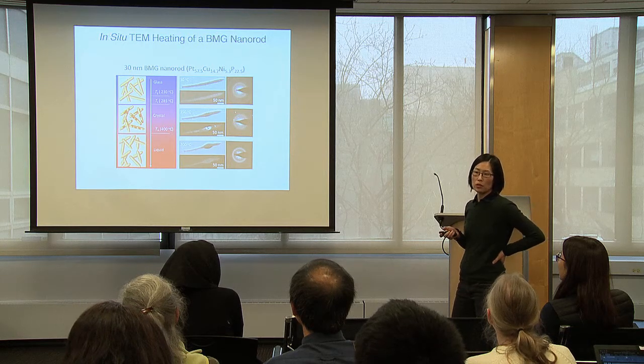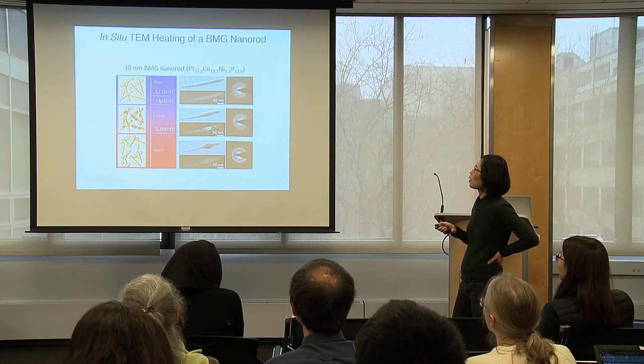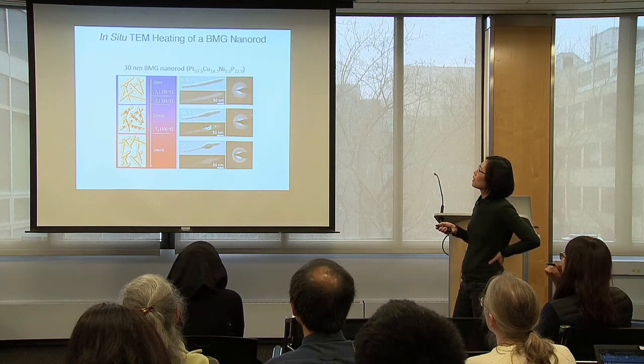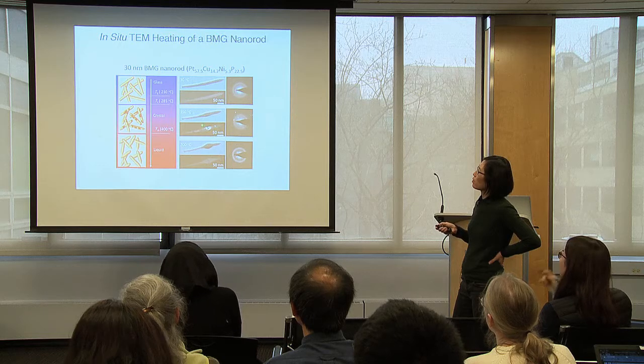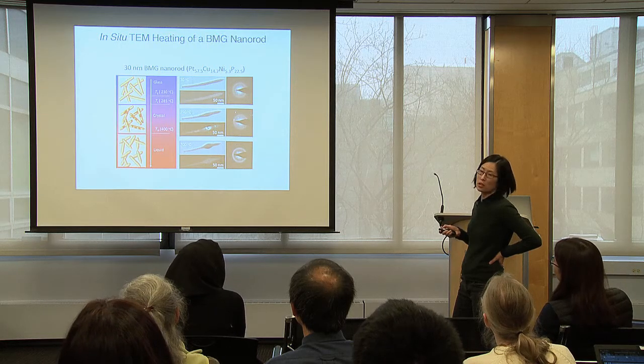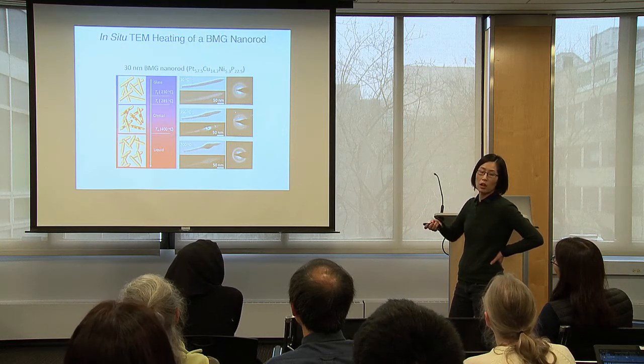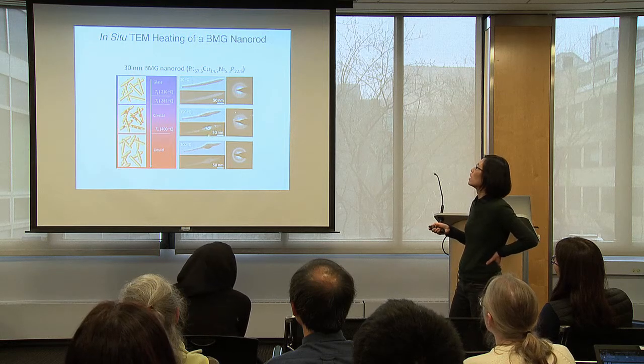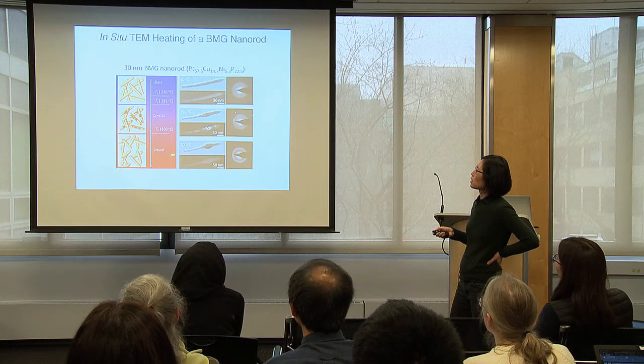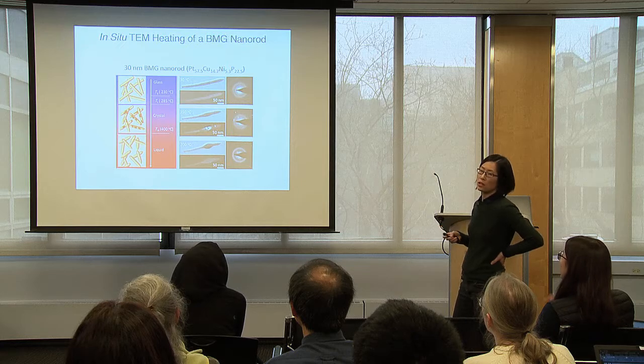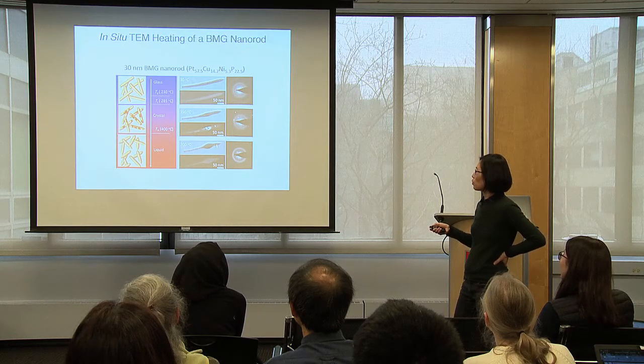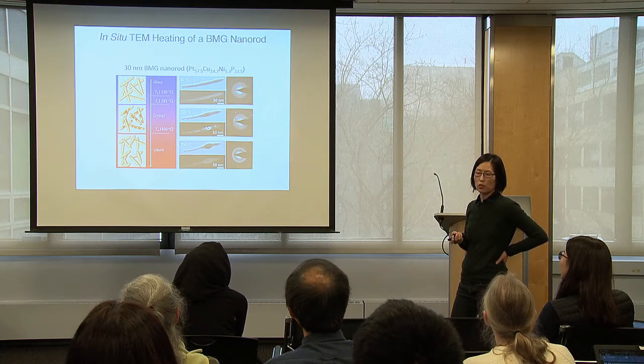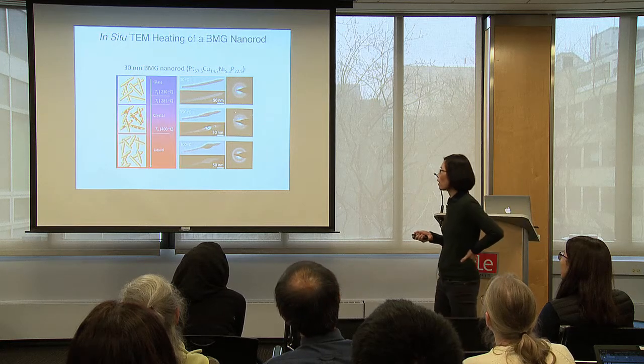Uniform contrast, so it's amorphous. Now I heat it above the crystallization temperature, so now it's sitting at 350. In dark field, it's now clear that it's much easier to pick up crystalline grain because there's an intensity contrast. It's a diffraction contrast. So the bright regions, you know it's crystallized. Now if you're at high temperature long enough, then it's going to melt and ball up because of the surface tension. It's liquid.